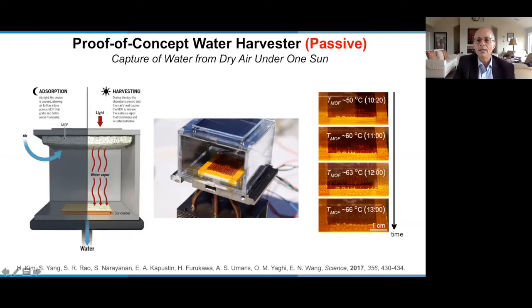The interior heats up, and as it heats up, as you can see here, the temperature of the interior is 50 degrees C, goes up to 66 degrees. And you can see as it heats up, the water droplets appear and they increase in size. In this experiment, we only used 2 grams of MOF. So 2 grams of MOF didn't produce a whole lot of water, but certainly the experiment worked. You can take this MOF outside the laboratory and show that in fact in low humidity, in this case 30% relative humidity, it does work.